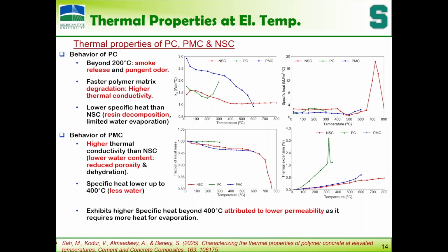Similarly, we did specific heat and thermal expansion, but notice that when it comes to polymer concrete, it is very hard to go beyond 200 or 300 degrees, even for the material property test. You cannot do this. A lot of smoke. Police were called to our lab when we were doing the test. Health and safety issues. The fire department came in and kicked all the samples out. We faced a number of problems; it is very hard at high temperature. It emits smoke, people get headaches, and nobody can be around.